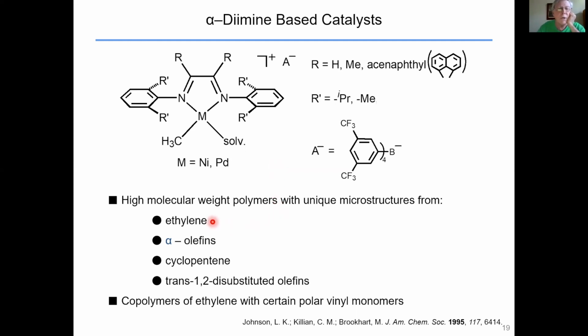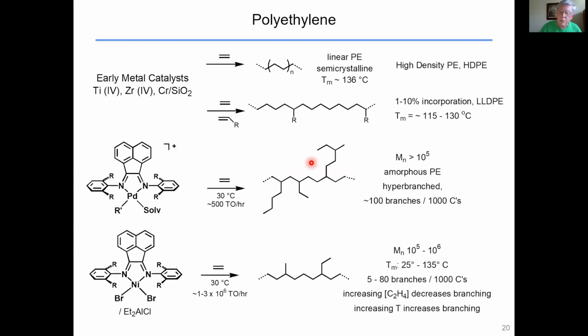We can polymerize ethylene or alpha olefins or various cyclic olefins, trans 1,2 disubstituted olefins, and we can copolymerize ethylene with certain polar vinyl monomers, and I'll show you a little bit of that chemistry later. So on the next slide, I'll summarize the kind of polymers that we make. Recall that with early metal systems, when you polymerize ethylene, you get strictly a linear semi-crystalline high density polyethylene. And if you want to put branches in, you have to copolymerize ethylene with an alpha olefin like 1-octene or 1-hexene to sprinkle branches along the chain and reduce the Tm